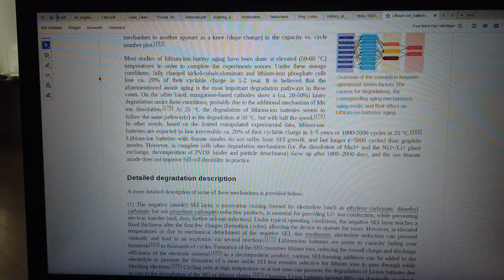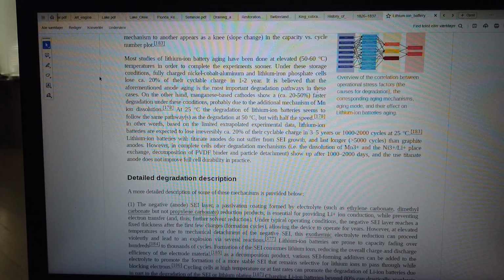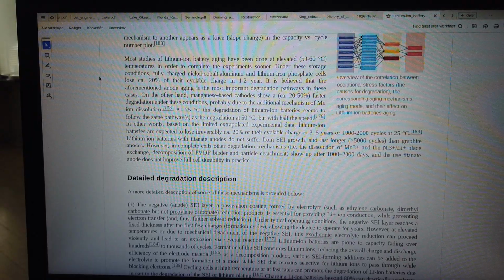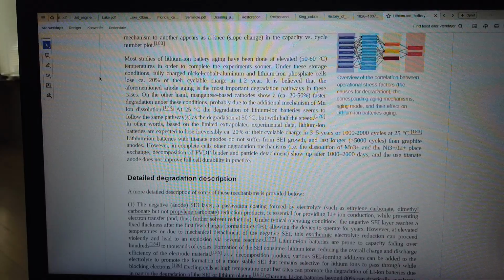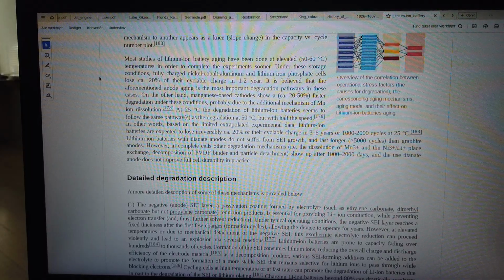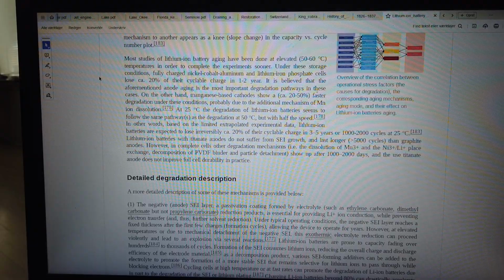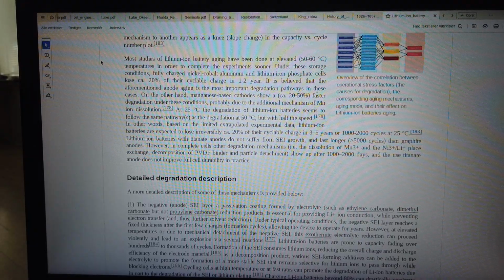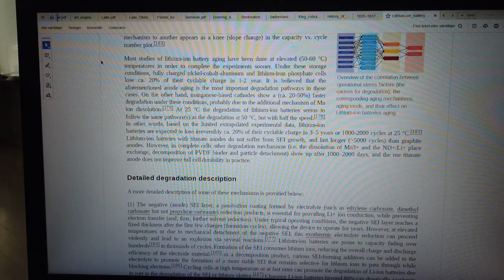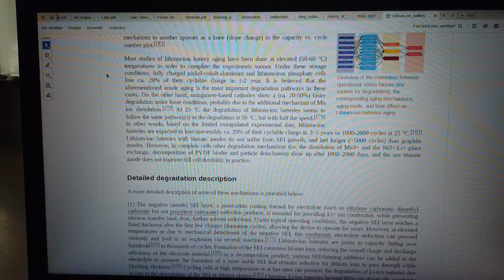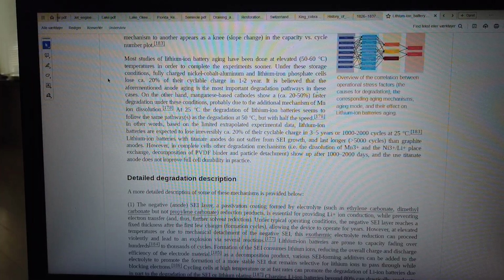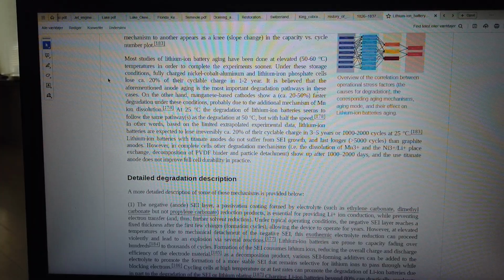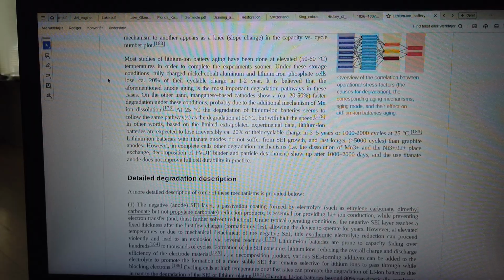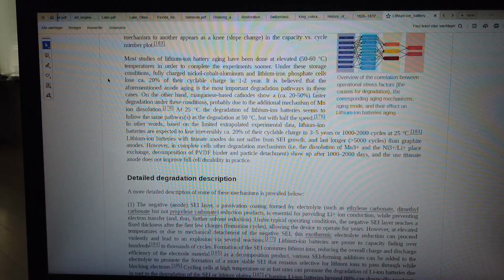Most studies of lithium-ion battery aging have been done at elevated 50 to 60 degrees C temperatures in order to complete the experiments sooner. Under these storage conditions, fully charged nickel, cobalt, aluminum and lithium iron phosphate cells lose about 20% of their cyclable charge in 1 to 2 years. It is believed that the aforementioned anode aging is the most important degradation pathway in these cases. On the other hand, manganese-based cathodes show about 20 to 50% faster degradation under these conditions, probably due to the additional mechanism of manganese dissolution.